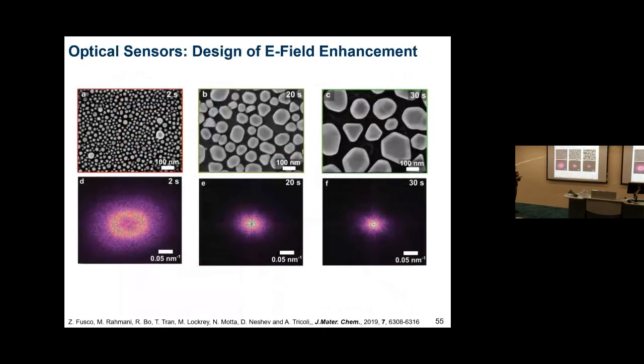We have also tried to characterize this and design the field enhancement, asking what happens at 2 seconds, 20 seconds, 30 seconds. As you can see, the spacing between these gold nanoislands changes, so the electrical field will change. There's a story about uniform disorder I'm not going to go into, but basically you can produce a uniform disorder, which means on a small scale it's disordered, but on a large scale it's reproducible, and that's what we see here.